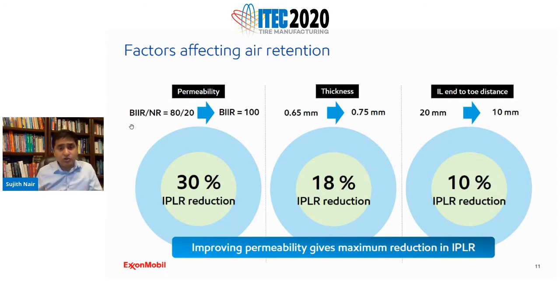Now, let's say you increase the thickness of your inner liner to make it better. Yeah, it's doable, but you can increase your thickness by around 20% and you still get only an 18% reduction in the IPLR. Please compare this to the earlier part where we changed the material composition. We were able to get a 30% improvement, whereas by changing the thickness by 20%, you're going to get an 18% IPLR reduction.